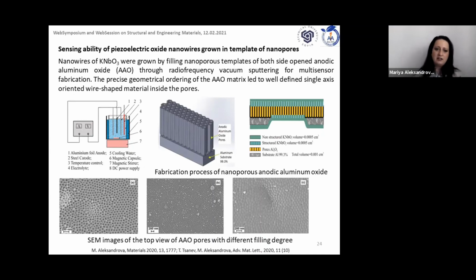That's why our last study is for building an array and matrix from nanoporous anodic aluminum oxide with controllable length and diameter of the pores. And we proposed that hollow tubes, nanotubes, are deposited from this material, and we started to fill in the tubes by sputtering two-sided from the top and back side in order to fill this tube to produce nanowires from the